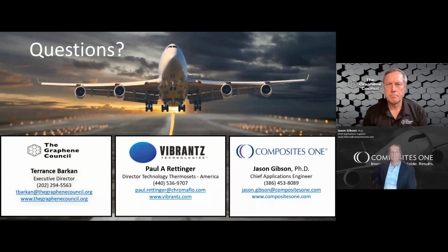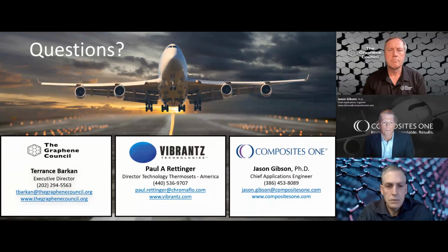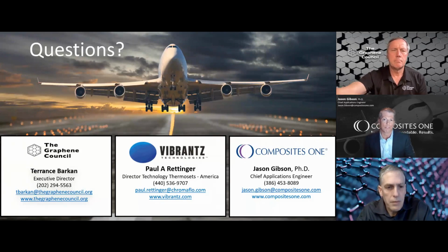In the study, how did you measure the agglomeration? So I'll answer that. What we were doing there was, under a microscope, we were polarizing the image. This particular digital microscope had the capability to polarize and then take that digital image and calculate that area. It's not 100% accurate. It's not perfect, but it's the only way we had to really give a quick analysis of the amount of agglomerations, the size of them, that type of thing. So that's how we did it. It was purely through the digitization of this particular microscope we're using at the University of Maine.